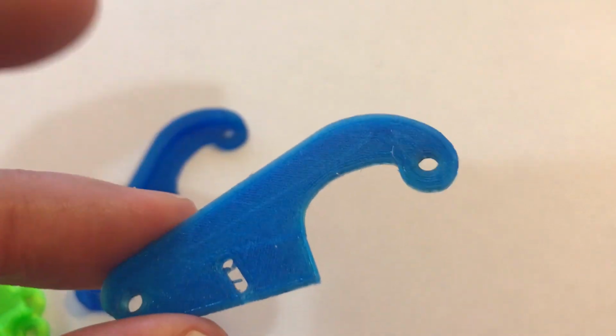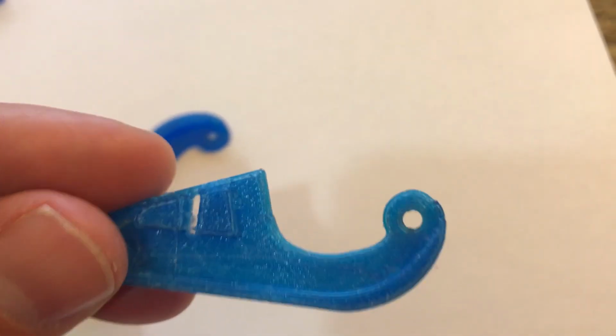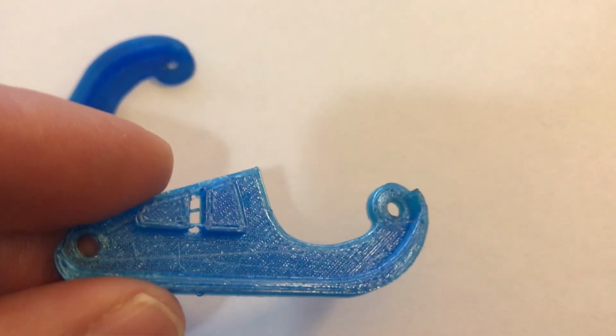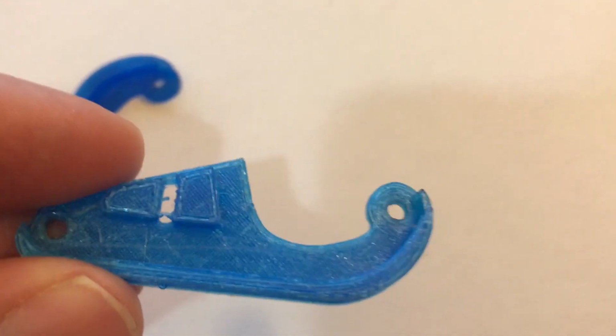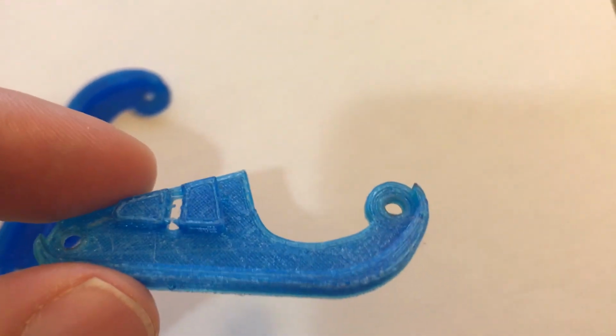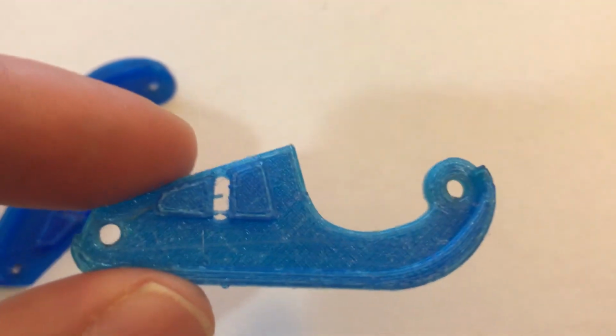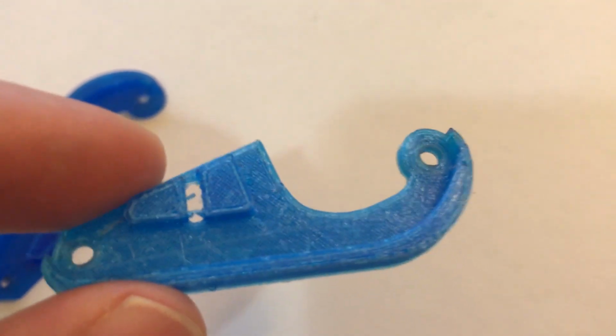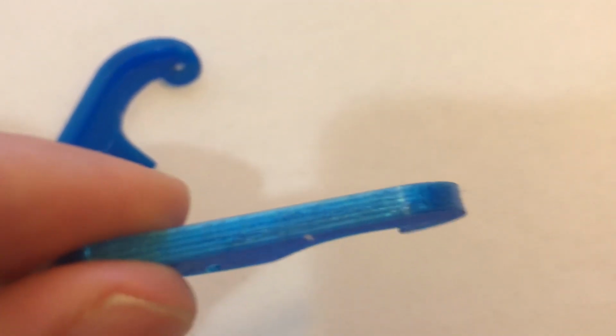This is one of them. This is an earlier piece that I printed, and you can see it's kind of stringy looking, kind of hollow. You can see it looks a little bit lighter in color because the layers just are not adhering to each other. There's a little bit of gap between the lines, and they call this under extrusion.